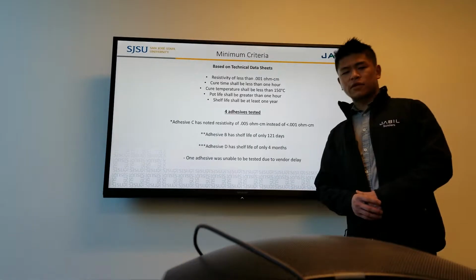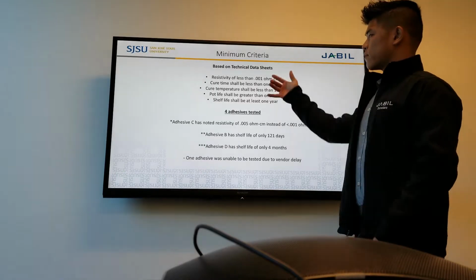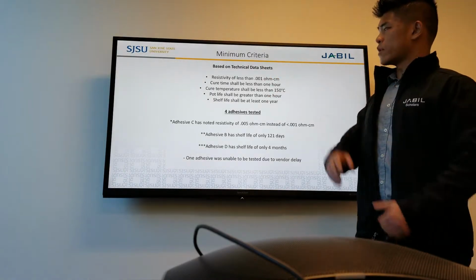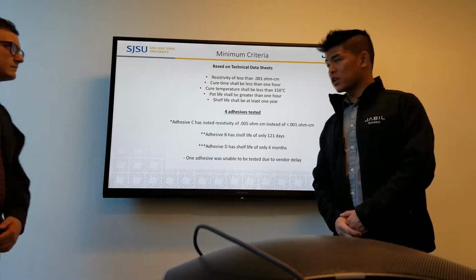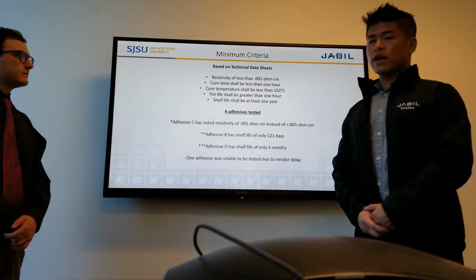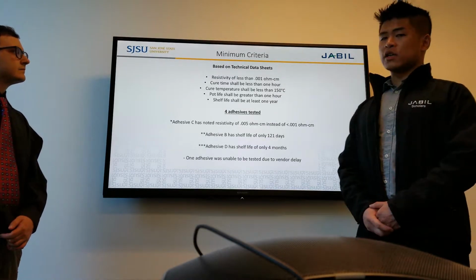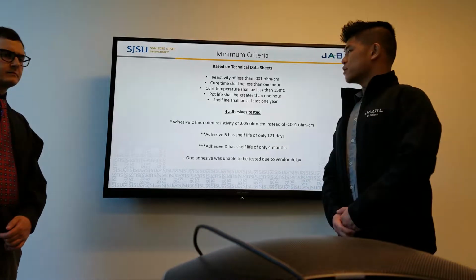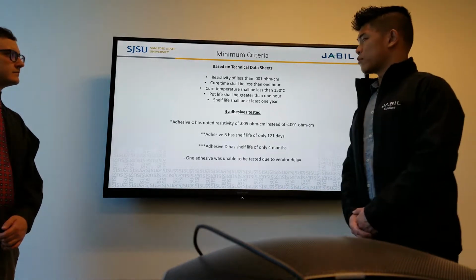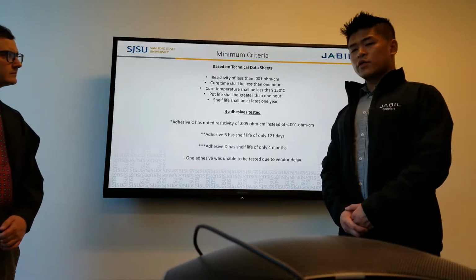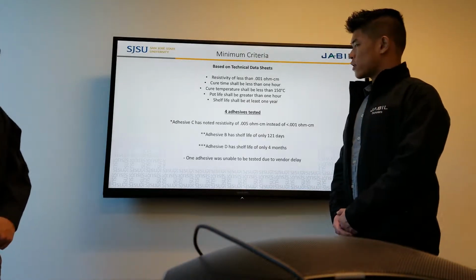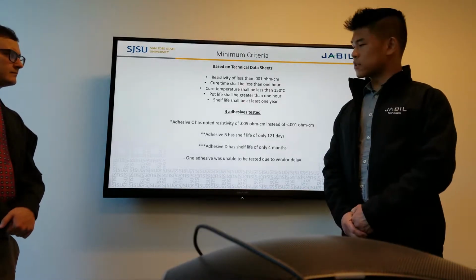Our minimum criteria for selecting adhesives are based on these 5 data points. It has to have a resistivity of less than 0.001 ohm centimeters. Cure time should be less than 1 hour. Cure temperature is less than 150 degrees Celsius because PET will degrade at that point, and we want to keep the temperature as low as possible. Pot life should be greater than 1 hour, and shelf life is greater than 1 year for manufacturability purposes.